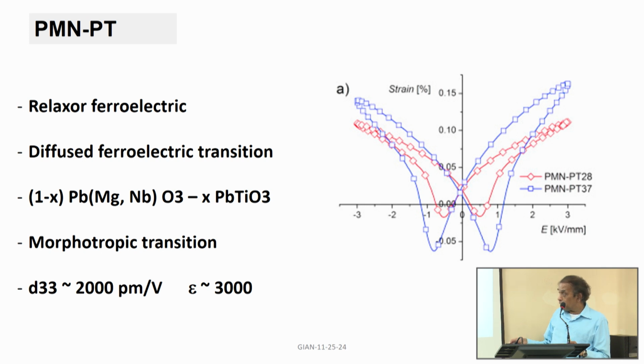So I want to point out here that the ratio of d to epsilon, 2000 divided by 3000, is 0.66. And some of the pure piezoelectrics such as quartz have a comparable value. So you may use quartz rather than PMN-PT because quartz doesn't have any lead in it. So it's not going to be a problem with cleaning up the environment compared to PMN-PT.